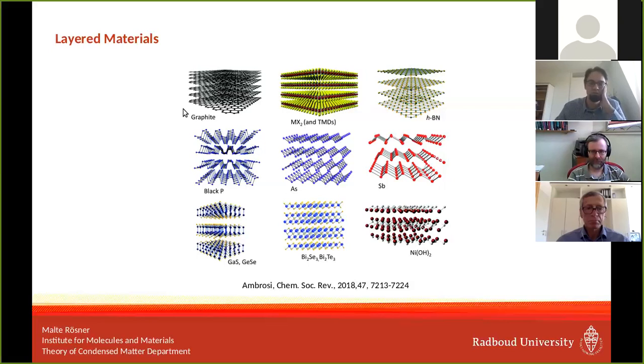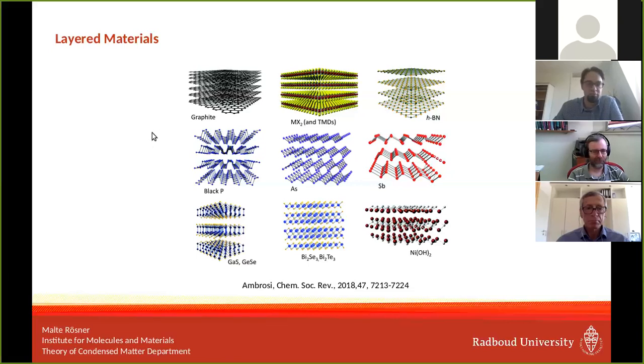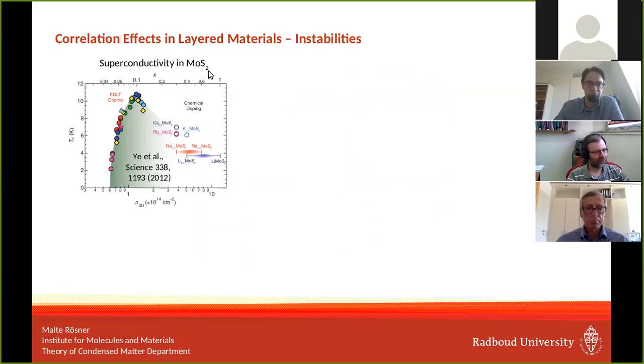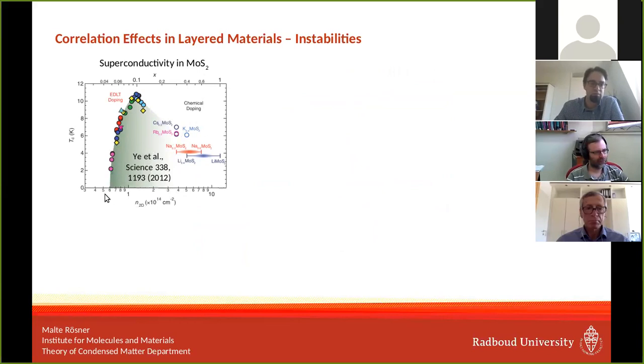With this whole zoo of 2D materials, a whole zoo of correlation effects enters the stage. On the many-body instability side, we find, for example, superconductivity in electron-doped molybdenum disulfide, which belongs to the transition metal dichalcogenide class. Molybdenum disulfide on its own is a semiconductor, but when we slightly electron-dope it, we find this superconducting dome with increasing transition temperature TC.